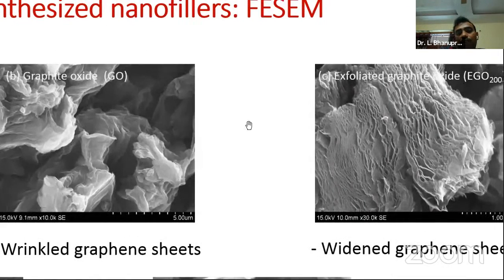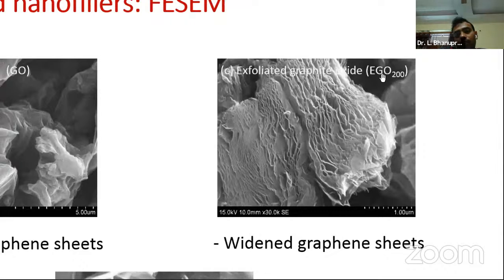And then we have exfoliated at 200 degrees centigrade. Suddenly this graphite oxide is brought to 200 degrees centigrade. Because of that sudden change, all the oxides present between these graphene sheets will be removed. As a result, it will exert some pressure between the sheets, and the sheets are expanded. You can see many expanded sheets.